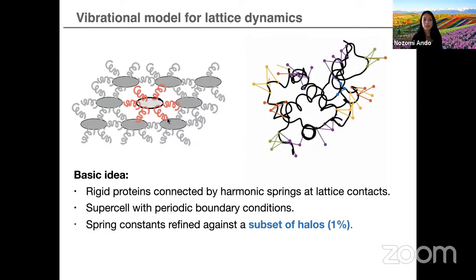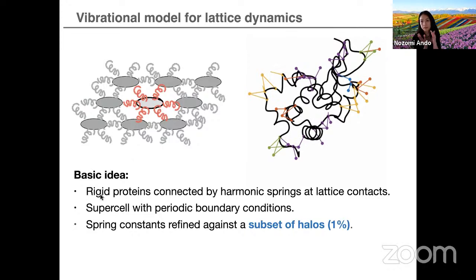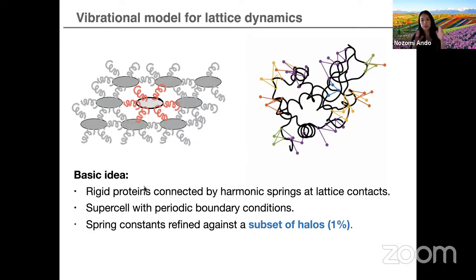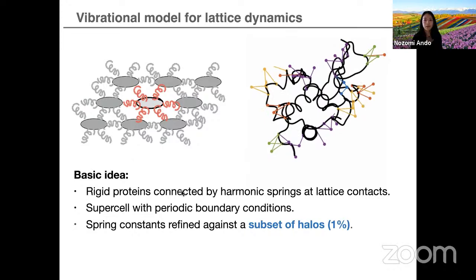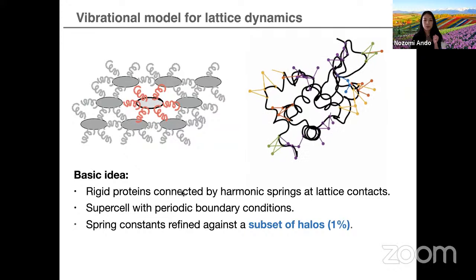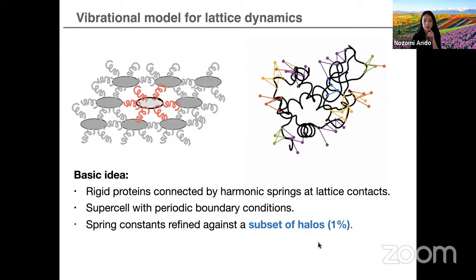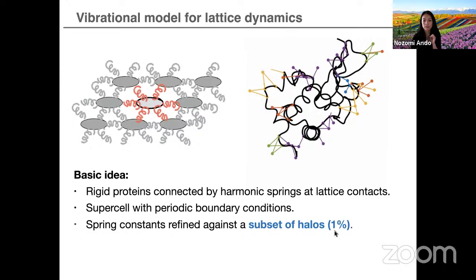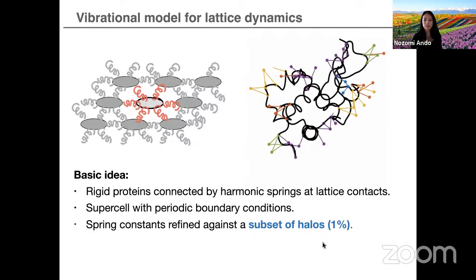And so it's undergoing some kind of vibrational force. And he also created a supercell and then imposed periodic boundary conditions. And then the very cool thing was that he actually refined the spring constants to the diffuse scattering, and not all of the diffuse scattering. He chose a very small subset of the halos. And for the crystallographers in the audience, this working data set of 1% is very small. But because these halos are three-dimensional, there's a lot of data per halo. And so that's what he did.